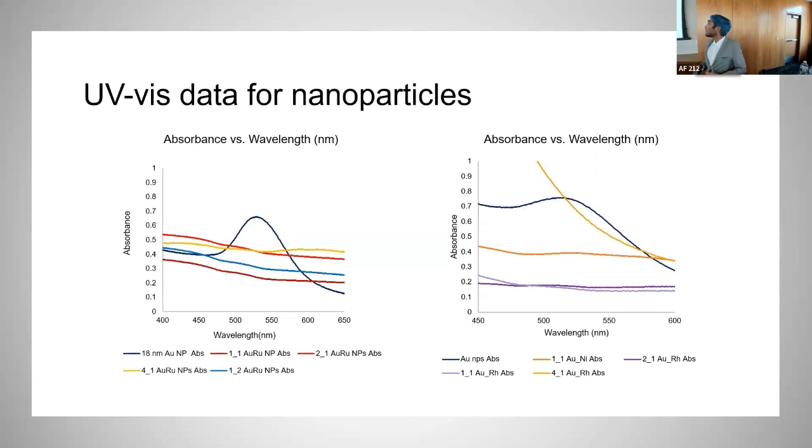So finally, I utilized UV-vis, and this is absorption versus wavelength. You can see how essentially the electronic structure changes for the gold nanoparticles, which absorb at around 522 nanometers, and how the core shell nanoparticles no longer have that plasmon resonance, which is a good indication that our shell structure is coating the core.